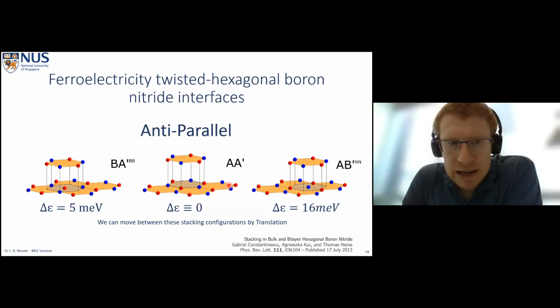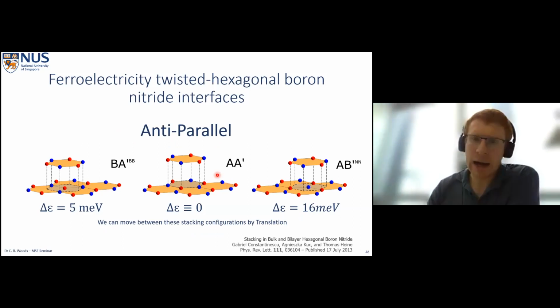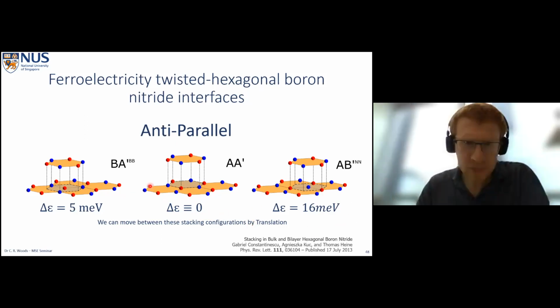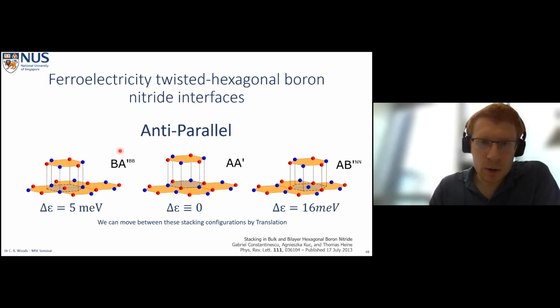And this is one of the 3 high symmetry stacking configurations that we can have for what's called the antiparallel configuration. So all antiparallel means is that if we have one layer, which is one orientation, then the adjacent layer will be rotated relative to that layer by 180 degrees. The definition of antiparallel. And as I mentioned, AA prime is our most energetically favorable stacking configuration. And so we define its binding energy, which is something around 90 meV, but I'll just say its binding energy is 0 here because we measure the binding energy of all the other stacking configurations relative to it. And for the antiparallel configuration, we can also have BA prime and AB prime stacking configurations.